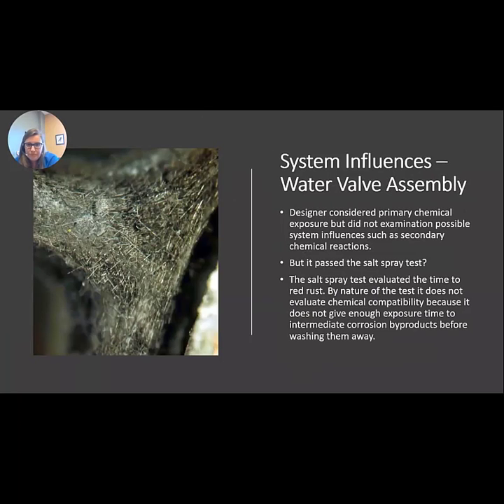So what did happen? So what the designer didn't know was that there was going to be secondary chemical exposure to zinc chloride. So zinc chloride basically forms as a corrosion product between zinc platings and road salts. And when you have zinc chloride and acetal, you have incompatibility. So this is a close-up photo of where that bolt had fallen out of the housing, and you can see you've got just glass fibers. All the resin that was there has been basically eaten away. So you're going to say to me, well, I don't understand. It passed the salt spray test. They did the corrosion testing.